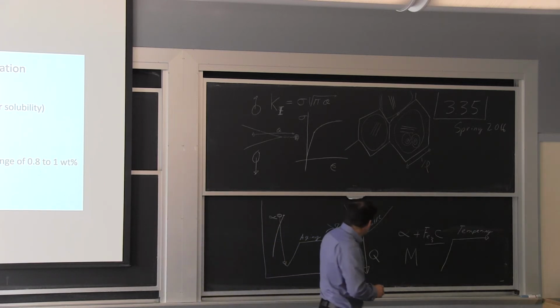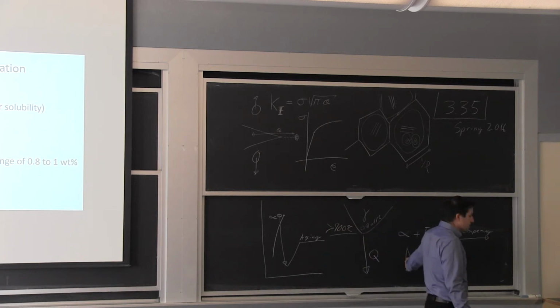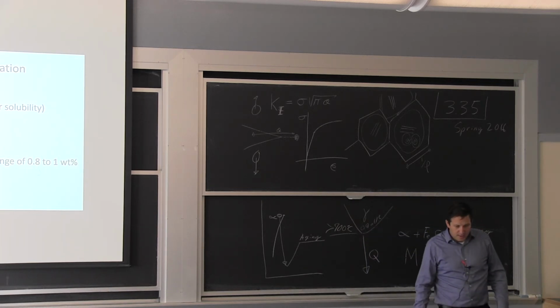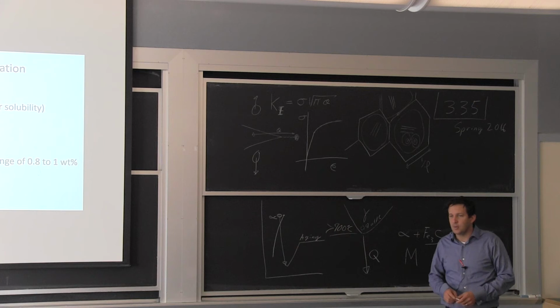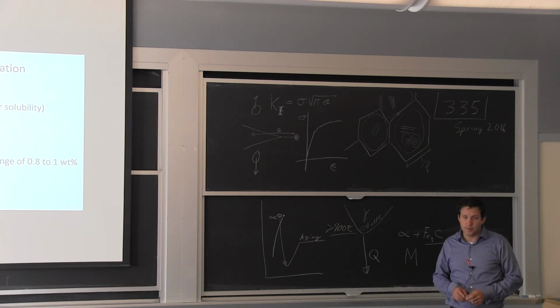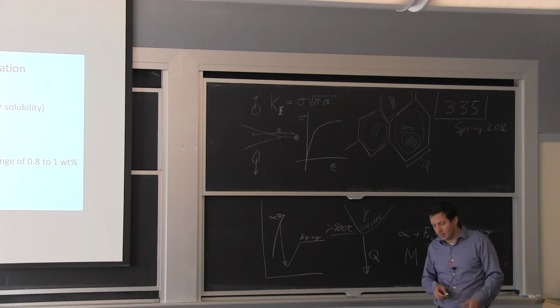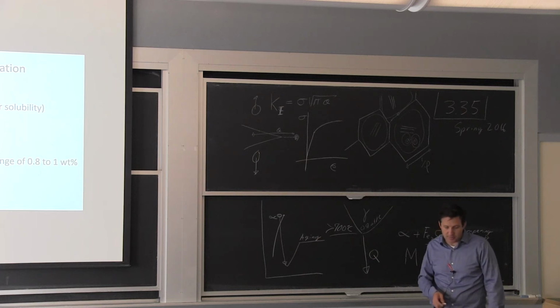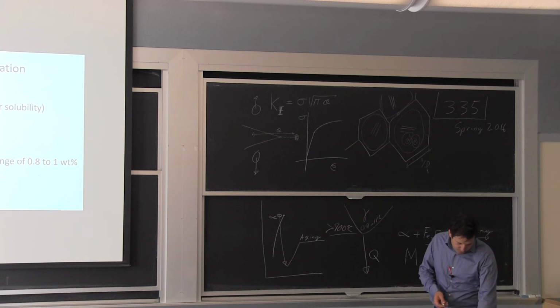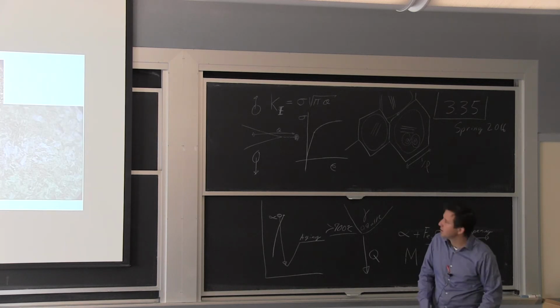And by cooling down quickly, we go through the same process here of forming the martensite. So now we have martensite on the surface, and it's a high carbon martensite. Martensite has different hardness depending on the carbon content. The more carbon you have, the harder the martensite is. So going to those threads, I'm going to just show you the microstructure right away.